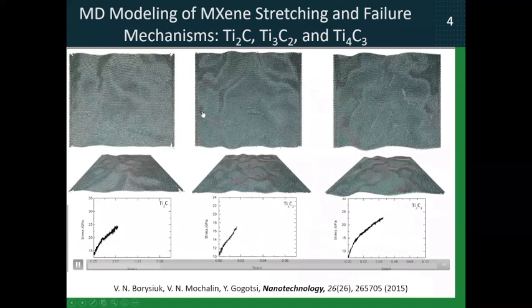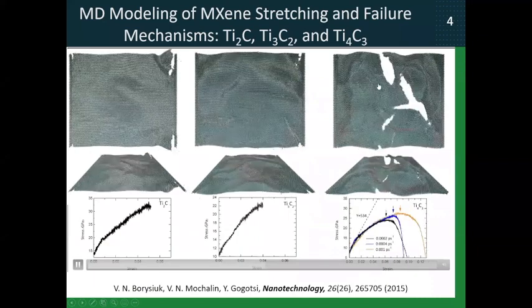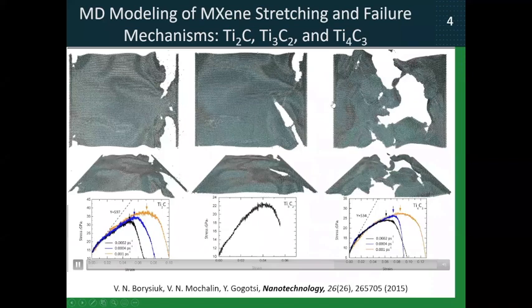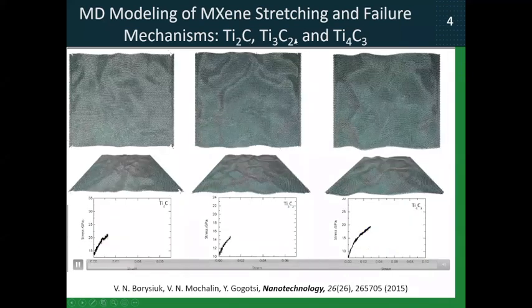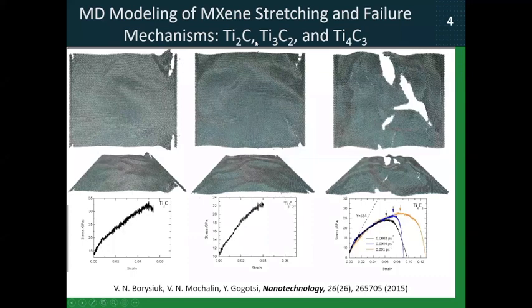Titanium 2C is on the left, then titanium 3C2 in the middle, and titanium 4C3 on the right-hand side. And you can see, even by looking simply at how they fail, of course, when you stretch them, eventually they fail. The failure mechanisms are very different between these 3 MXenes. Now, they all have same elemental composition. It's titanium carbon MXenes, right? And the only difference between them is the variations in monolayer thickness. As I said, MXenes allow precise tuning of this.